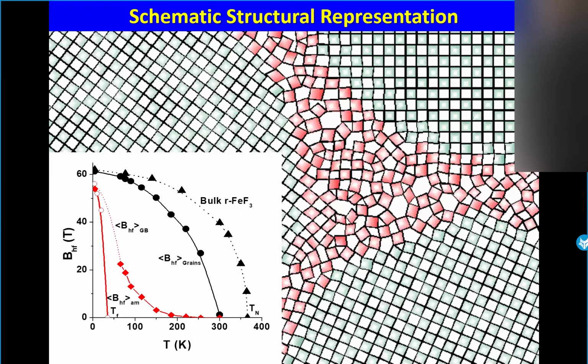So, we have the evolution of the bulk FeF3. We have the evolution of the hyperfine field of the crystalline grains, which is a bit lower, probably due to some superparamagnetic relaxation phenomena. We have the amorphous, which goes down to 29 Kelvin, and we have the contribution of grain boundaries.